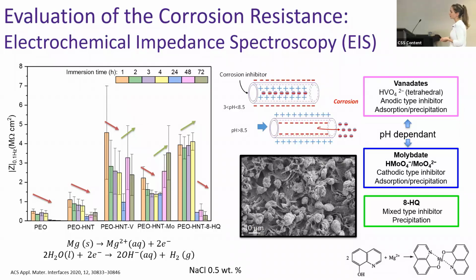In the case of the organic inhibitor, the behavior is completely different to the previous one. We can see that the corrosion resistance slightly increases during the first 4 hours, and then it drops to values similar to the inhibitor-free coating. So probably, as I mentioned before, all the inhibitor was completely released to the media at the very beginning of the experiment, and since there wasn't any specific trigger, after 4 hours of immersion, its effect was completely exhausted.